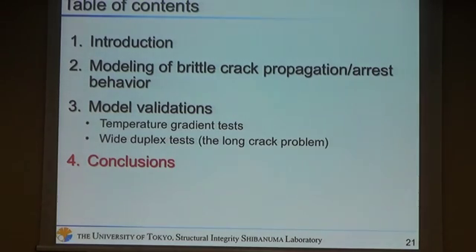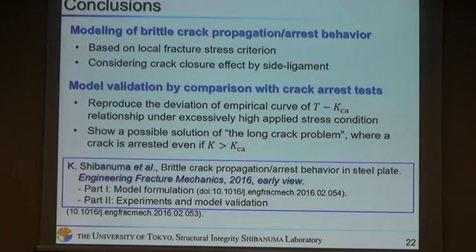Finally, I will conclude this presentation. In this study, we propose a model of brittle crack propagation and arrest behavior based on the local fracture criterion concerning the crack closure effect by side ligament. In the model validation by comparison with the crack arrest test, the proposed model can reproduce the deviation from the empirical curve of the temperature and arrest toughness KCA relationship under excessively high applied stress conditions. And this model shows a possible explanation of the long crack behavior, where the crack is arrested even when the stress intensity factor is larger than the arrest toughness KCA.